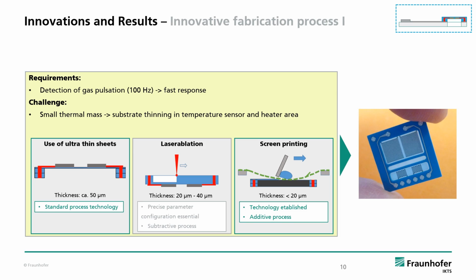The first one is the standard process technology with the use of ultra-thin sheets. The thickness is here 50 microns, which results in 40 microns after sintering. The second process is laser ablation. Here we can gain a thickness of about 20 to 40 microns of the membrane. The disadvantage is that a precise parameter configuration is essential and it's a subtractive process.